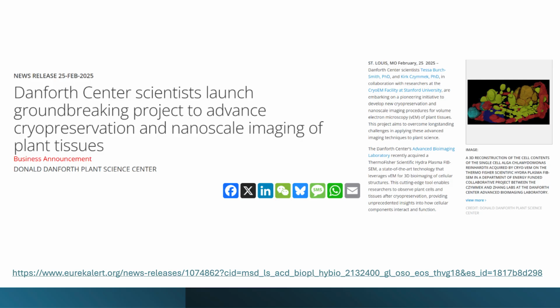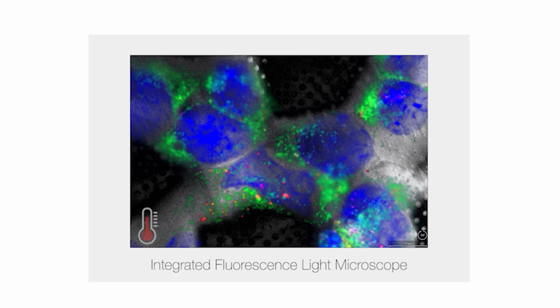But in situ cryo-electron tomography requires us to go in and extract materials from the cell in a very precise location. A lot of our structures that we're looking at have fluorescent proteins or some fluorescent component to it. And when you're doing cryo mode, you have to be able to find your target. And we often use the integrated fluorescence light microscope that comes with the Hydra to locate those things and get to them very quickly and efficiently. That's a very useful add-on. You can be more efficient and you can avoid annoying artifacts like contamination when you're transferring a sample from an external light microscope to your FIB-SEM tool.